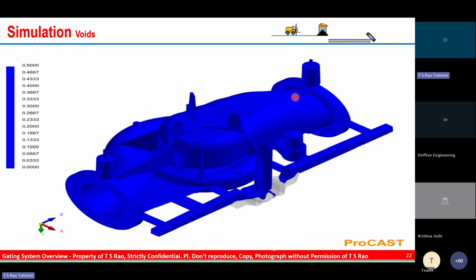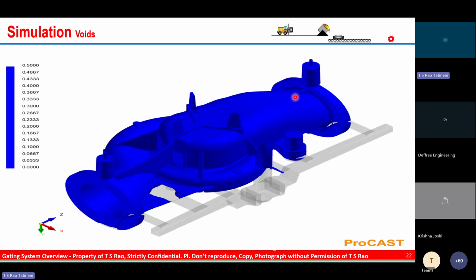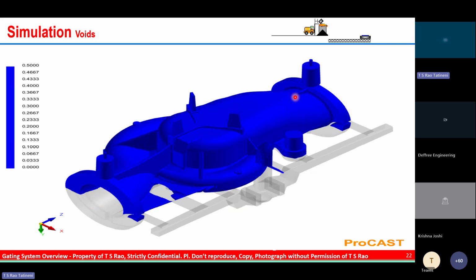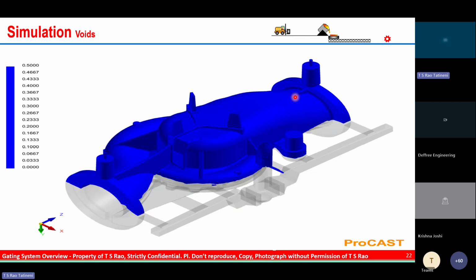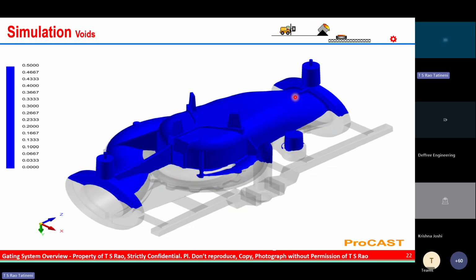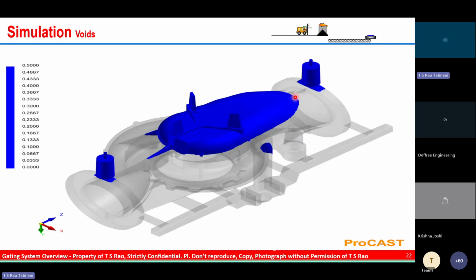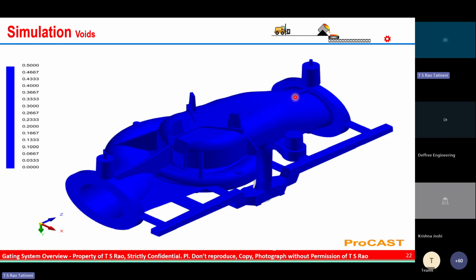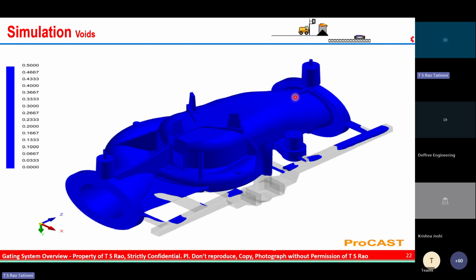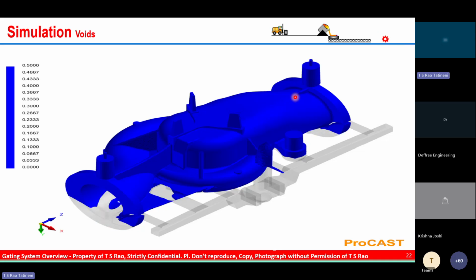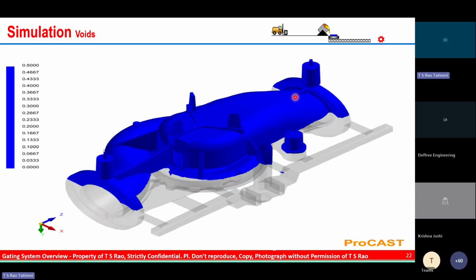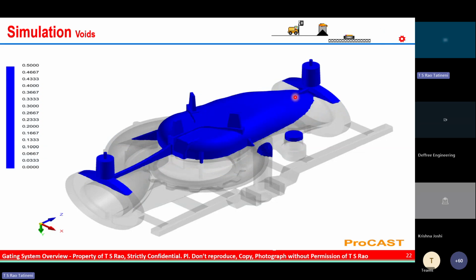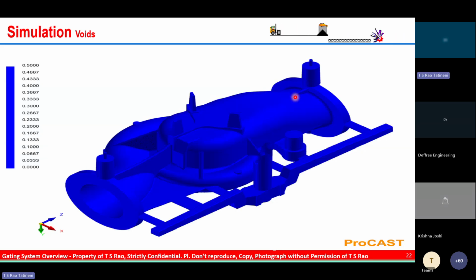The next slide is on the voids. Voids also happen because of the velocity or because of the air entrapment. Here you can see there are no voids. The hot metal has a laminar flow, and it is getting filled within the mold environment uniformly to ensure that there are no voids in the mold.